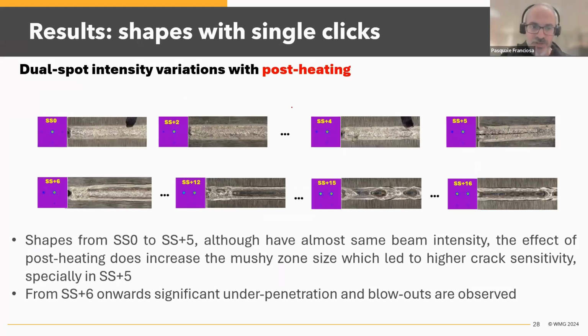Okay, so those are some of the images taken from the top. It's interesting to see that when we start with the central spot, there is a nice fusion. Then as we keep moving the spot towards the right-hand side, we are adding more post-heating. Still there is no significant central line crack. However, when you go to position 5, the post-heating is more aggressive.